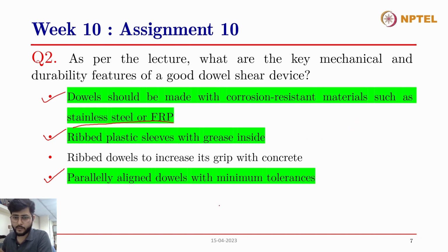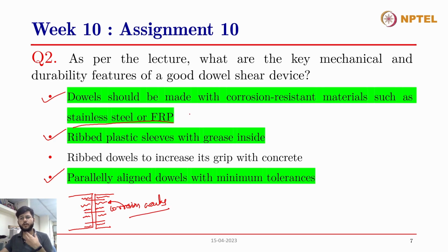So if I'm looking at a plan of an expansion joint, and this is a typical expansion joint with these dowel rebars, if corrosion occurs, then there will be longitudinal cracks across these rebars, and that will affect the concrete. So that will further allow the ingress of water and other substances into the concrete, and that will lead to the deterioration. So these are corrosion cracks. We do not want that, and therefore we want the dowel bars to be made out of corrosion resistant materials like stainless steel or FRP bars, right?